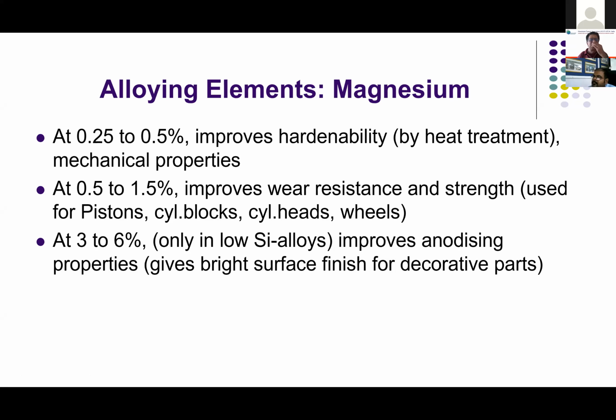Hardness of about 95 to 110 BHN is required for getting a very good machined surface in LM25 castings. Make it, let us say, cylinder heads. Cylinder heads made of LM25, you require a hardness of 95 to 110. Now, if the magnesium drops below 0.3, you will find it difficult to achieve a hardness of 90. Whatever you do in the heat treatment, not possible. Therefore, I always tell the people, maintain magnesium above 0.3, above 0.35.